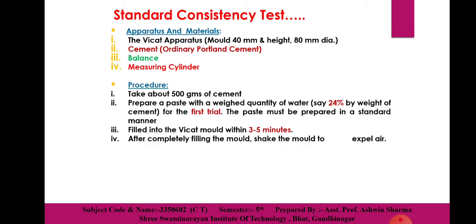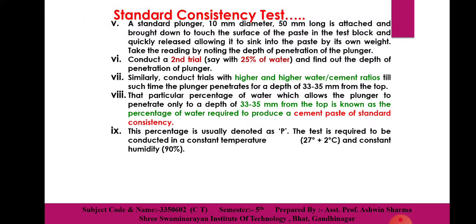After completing the filling, shake the mold to expel the air. The standard plunger of 10 mm diameter and 50 mm length is attached and brought down to touch the surface of the paste in the test block, then quickly released to allow it to sink into the paste by its own weight.